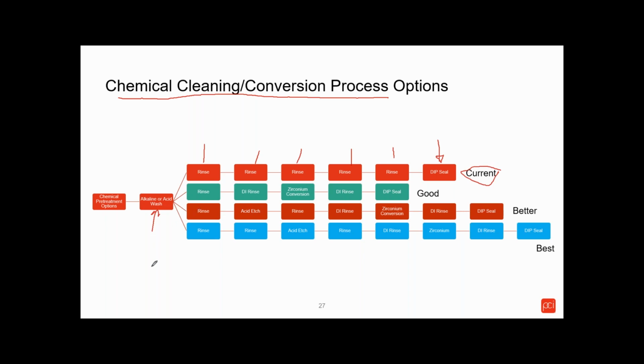An option to that would be using the same acid wash and going through a rinse, a DI rinse, preparing it for a good zirconium conversion coating, as we said, to improve performance and process flexibility. Then rinse it again, and then apply that same dry-in-place sealer to promote good adhesion to stainless steel, and we call that a good pretreatment.